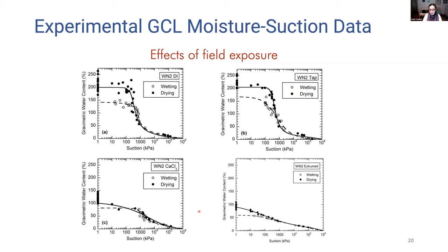A similar response also occurs for the field exhumed material. This is not exposed to any chemicals. This has just been sitting in the ground for an extended period of time and has been interacting with the over and underlying soils, this GCL. In this case, again, the saturated moisture contents are much decreased. Hysteresis is decreased again significantly, and water contents overall are lower than the water contents associated with testing with DI or tap water.